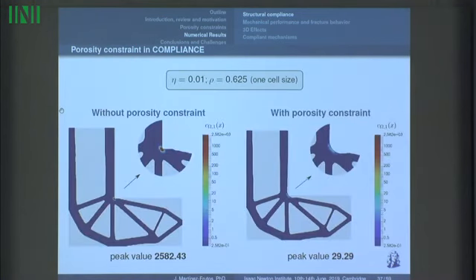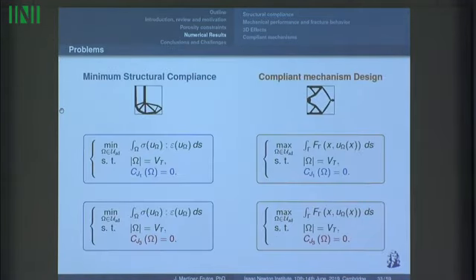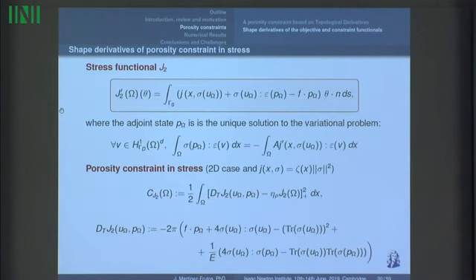So these results were achieved with this configuration, with the value of eta equal to 0.01 and the size of the porosity rho equal to 0.625, which is the size of one cell of the mesh. You can choose, of course, other sizes for this rho, but remember that we have a parameter eta rho in the constraint. Let me go back. Here, this eta rho is the only thing that matters from the numerical point of view.